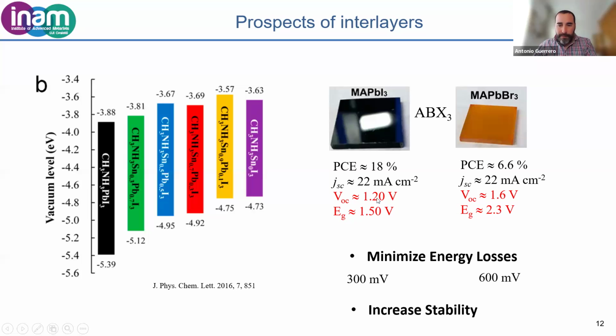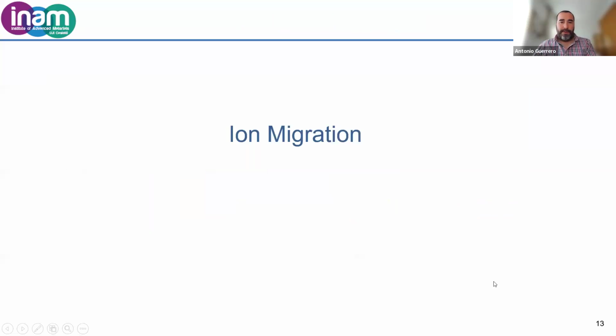Comparing the band gap with the open circuit potential we can get with these devices, with the MAPI, the methyl ammonium lead iodide perovskite, we only have 300 millivolts of energy losses, whilst for the bromide we get 600 millivolts of energy losses. We believe we don't have adequate transport materials for these formulations, and this is why these losses are still quite high, and we think we could get even higher open circuit potentials with this type of formulation.